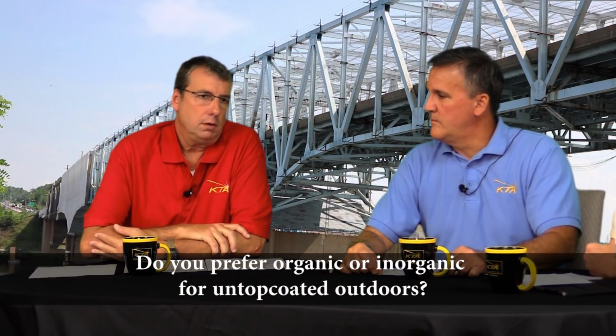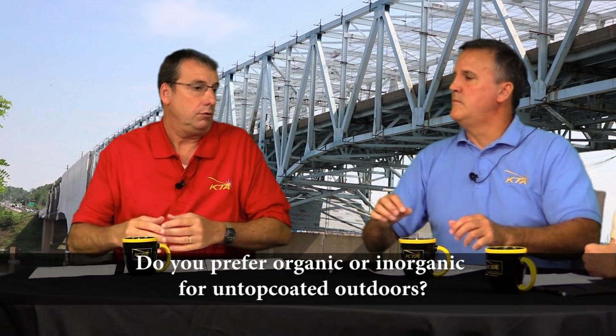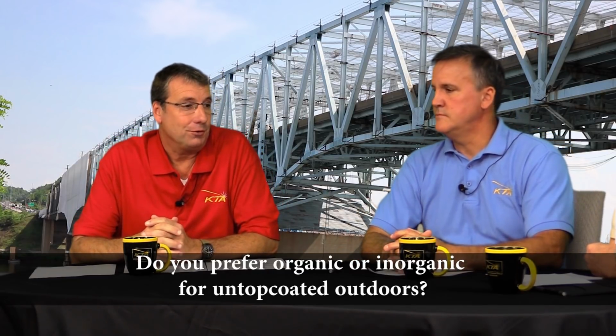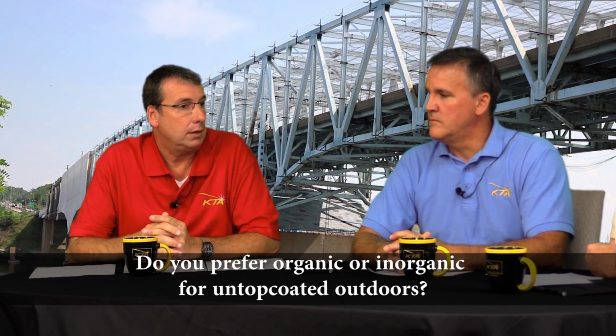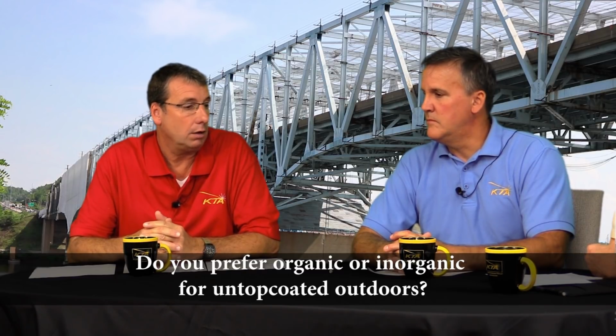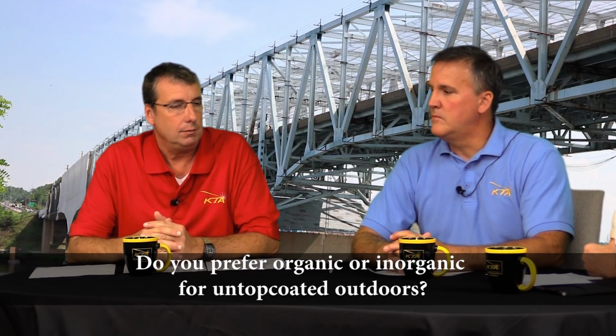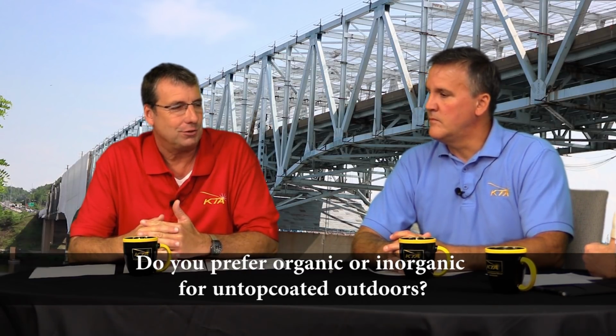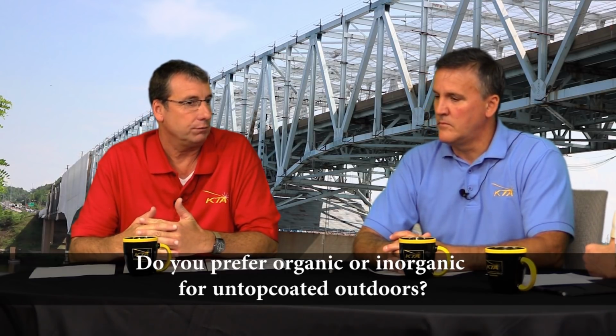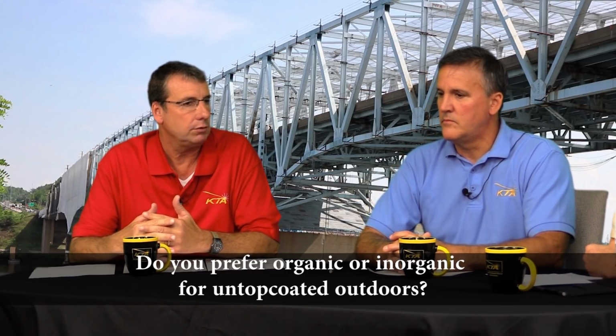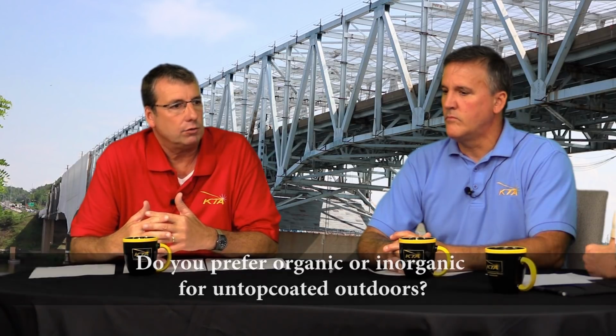Well, I guess I can make an argument for using inorganic zincs. They can be used outdoors as long as you're not concerned about aesthetics, because the zinc is going to begin to oxidize very quickly, but it's not going to oxidize uniformly across the surface. You're going to have a streaky appearance, but again, that oxidation will help fill some of the pores, and it's just the nature of the type of coating it is.